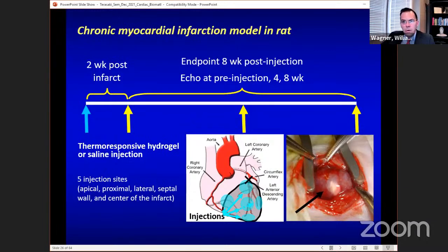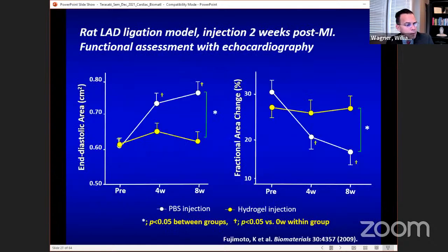We don't do the whole open surface of the ventricle, which some people have done clinically and in some large animal models. Don't see a reason to do that. You don't want to mess with relatively healthy myocardium. So here's that echocardiographic data like before. End-diastolic area, hydrogel injection, you pretty much hold that steady. Our control here is saline. So very similar procedure, except now we're just injecting a similar volume of saline. And then if you look at the function, you hold it steady with the gel and you lose function if you put in saline.